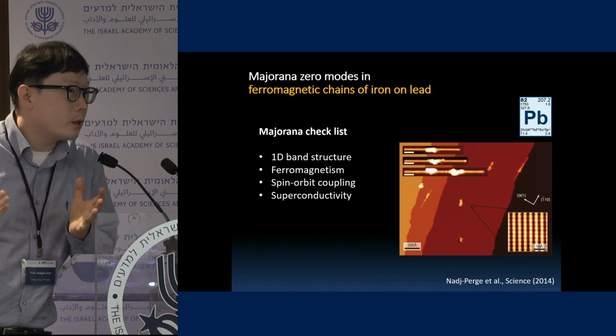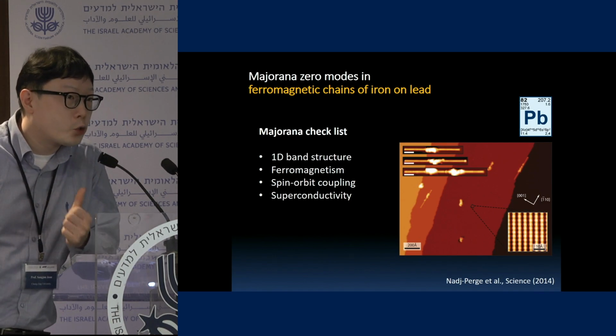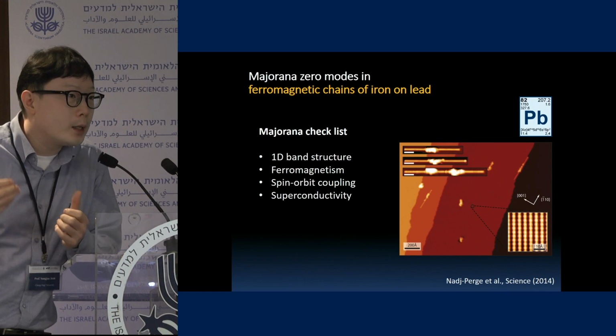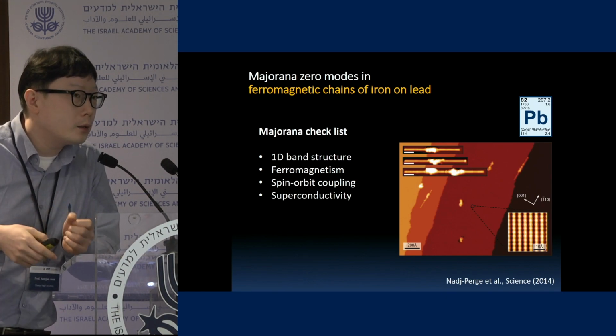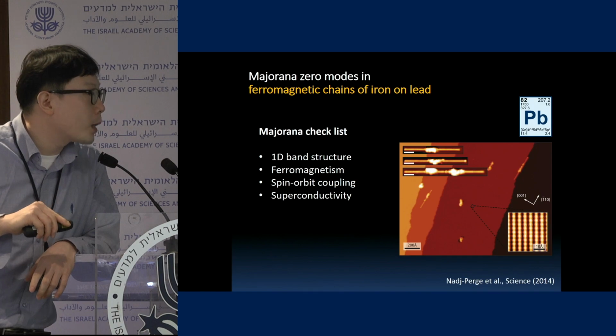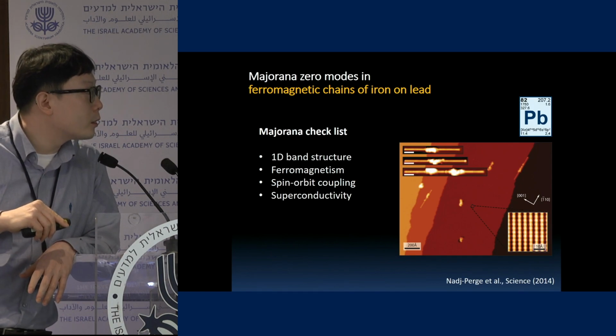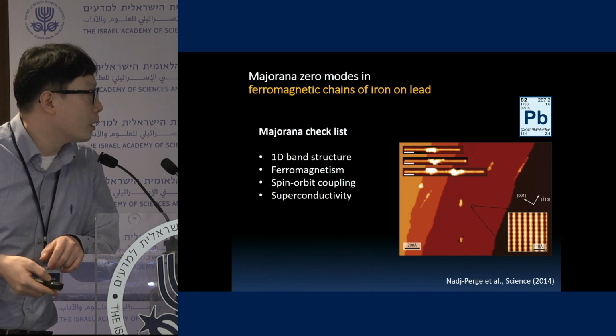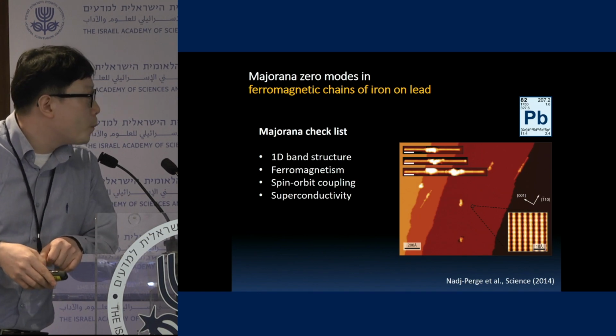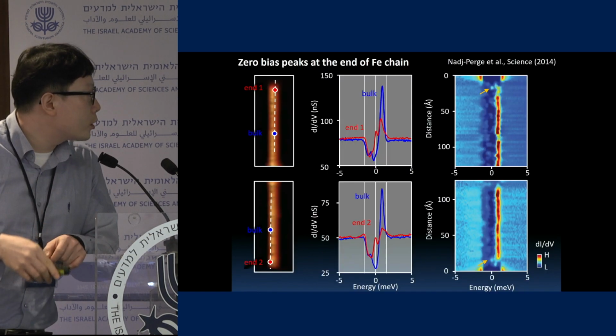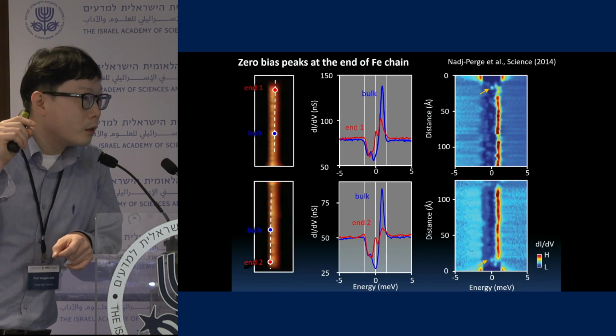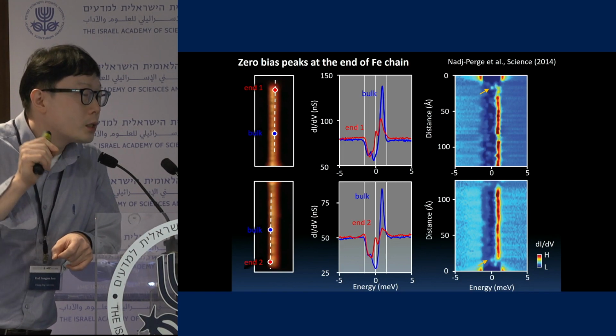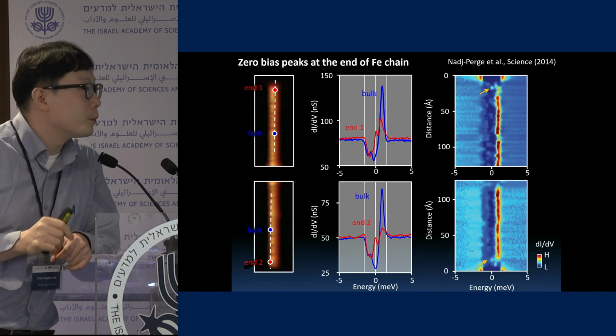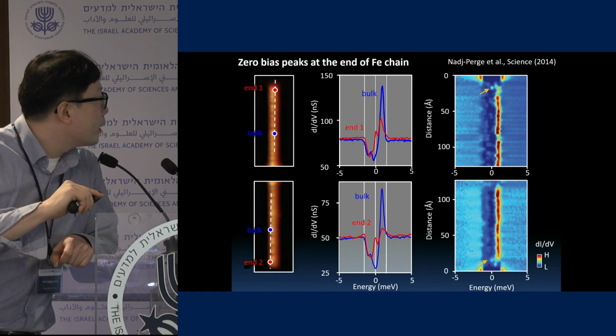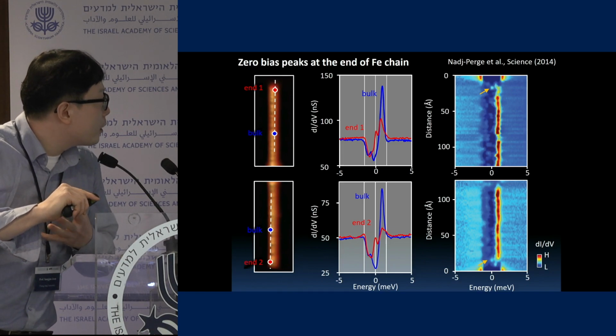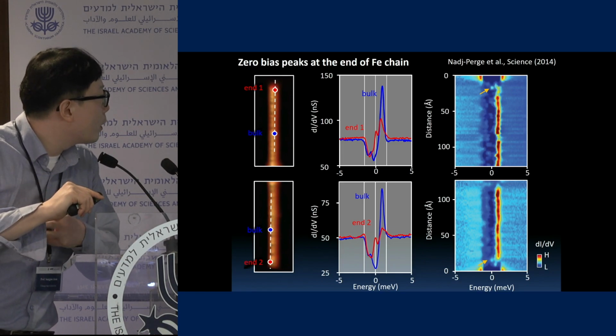So we have all kinds of ingredients in there. We have very strong superconductivity, and we have a one-dimensional magnetic chain on it, and probably we have some kind of strong spin-orbit coupling inherently from the lead element. So right after we got these structures, we directly measured the spectroscopic signatures of the zero energy state, and it turns out that we can very robustly find a localized zero energy state.